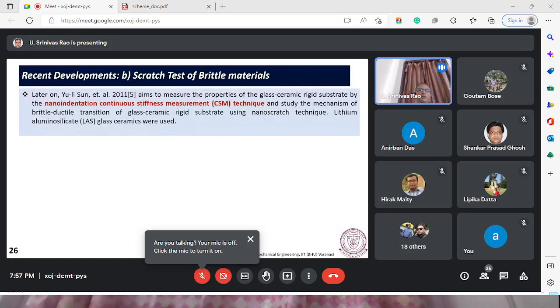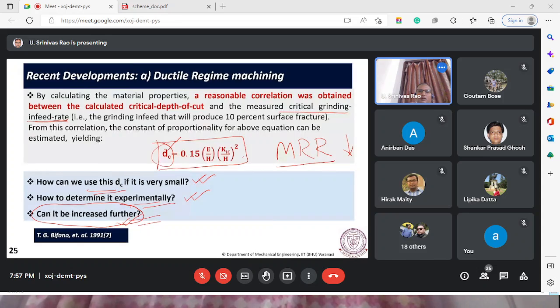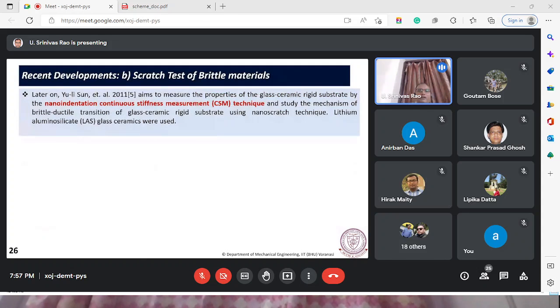And to determine the value of this DC, we have used scratch tests of brittle materials as well. Indentation test, then scratch test, and in the scratch, the width and depth of the scratch give an estimation of the DC, the critical depth, or in a way the threshold value of the brittle-ductile transition. So these nano scratch techniques are important.